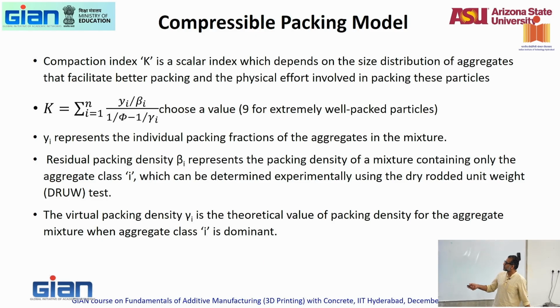Okay. Now, in that, you have a few terms. Here, y sub i represents the individual packing fractions of the aggregate. So, assume that I have number 8, number 4, 3/8, half an inch, all different sizes of aggregates. Assume that I have sieved them separately and put them in 4 different clusters. Now, typically, what you have in a ready-mix concrete plant are at least 2 different coarse aggregate gradations. Have you gone and seen a ready-mix concrete plant? Have you seen their aggregate piles? You have at least 2 aggregate piles, if not more. If you're doing much more controlled concrete mixtures, if you're doing UHPCs, you may have 4 or 5 different bins. Otherwise, you'll have 2 bins corresponding to 2 different coarse sizes, and you have a fine aggregate bin as well.